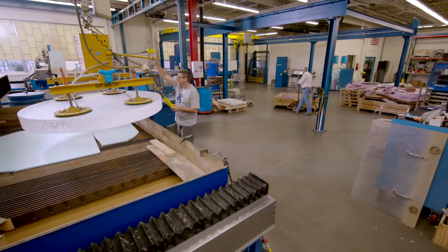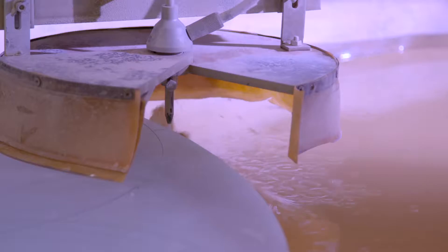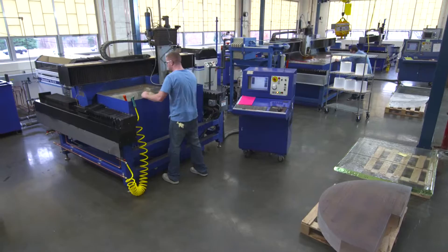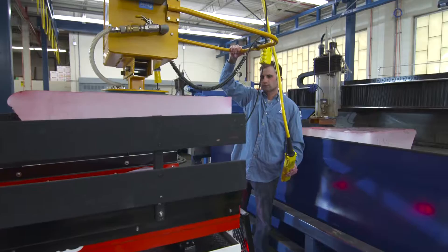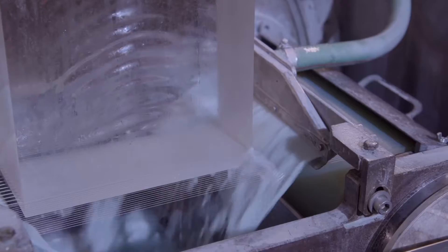Much of our inventory is received in very large boules, sometimes up to 2,000 pounds. These can only be safely handled using our overhead cranes and placed onto our water jets to be cut into manageable sized pieces. Cutting out of the nozzle at 48,000 pounds per square inch, we're cutting glass 12 inches thick. Our overhead crane allows one operator to run all three machines. In order to cut wafers efficiently, we now employ the use of six wire saws, one of which is a multi-wire diamond wire saw. This is used to cut ultra-hard materials such as sapphire.